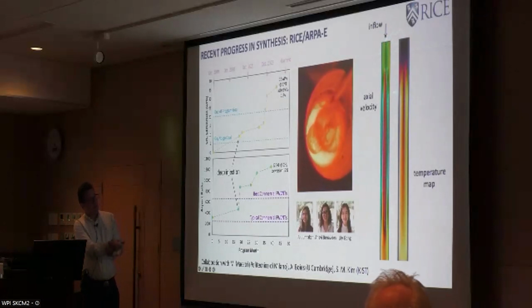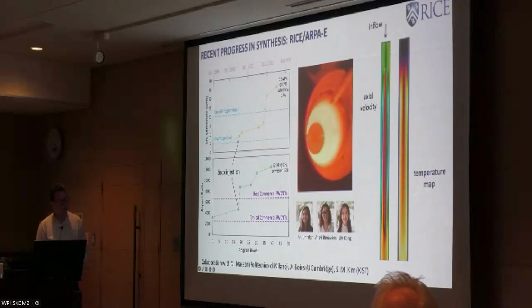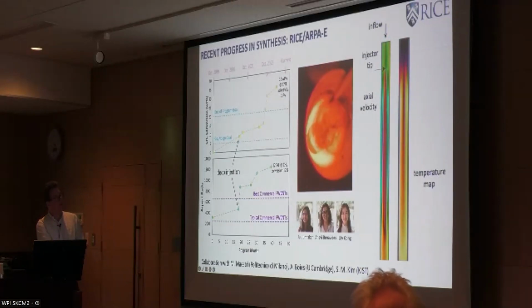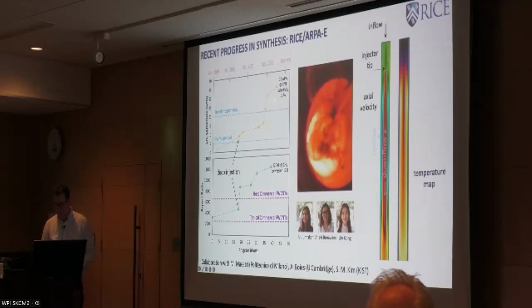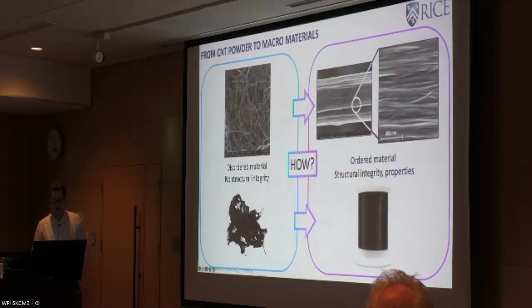But there is also a recirculating flow that brings the gases from the bottom to the top, and the gases on the bottom are hotter, and so these are actually bringing heat up in the front of the reactor. Injection has to be done deep into the reactor to avoid the recirculating zones and make the carbon nanotubes that you want. And what you see is that understanding what happens in the reactor brings productivity to much higher levels, and also the quality of nanotubes to much higher levels.